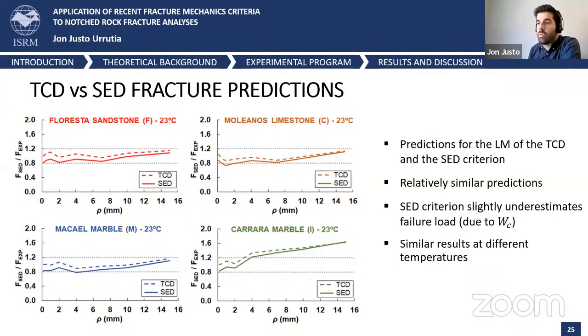If we compare both results, in this case, these are the results for 23 Celsius degrees. We can see relatively similar results of both methods. The dashed lines correspond to the theory of critical distances, and the solid lines represent the strain energy density criterion fracture predictions. We can observe that the strain energy density criterion tends to slightly underestimate the failure load compared to the theory of critical distances. And another drawback of this method is that it requires the deformational parameters, while the theory of critical distances only requires the fracture toughness and the tensile strength.